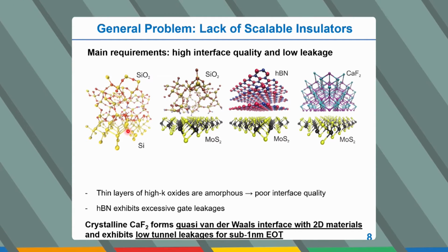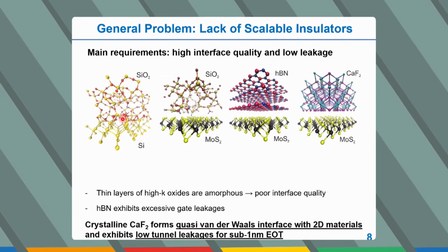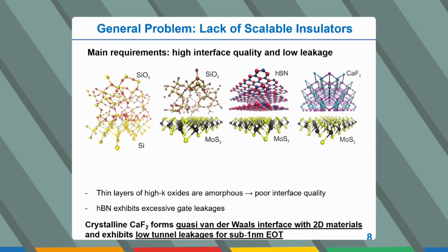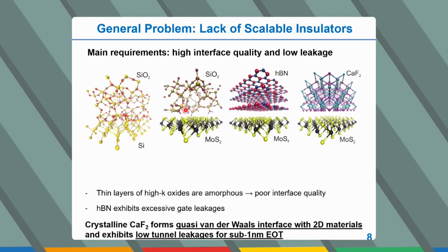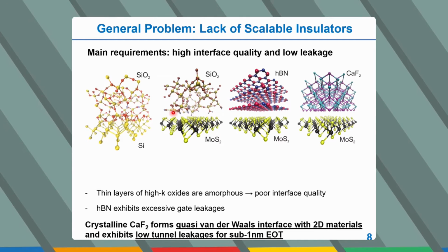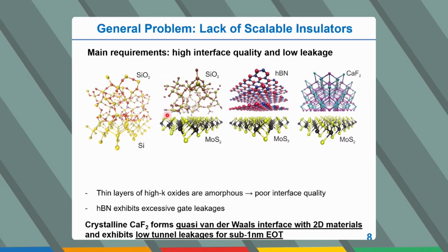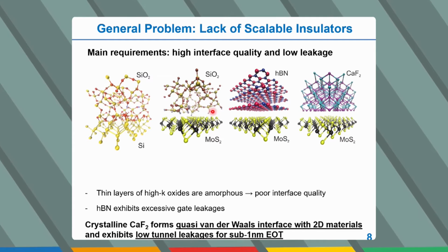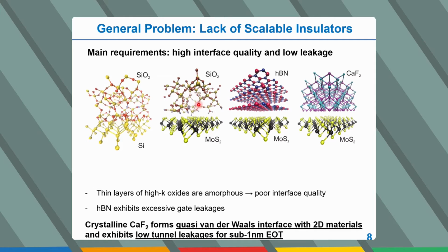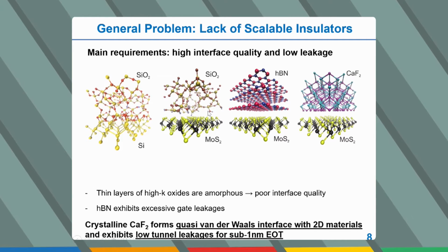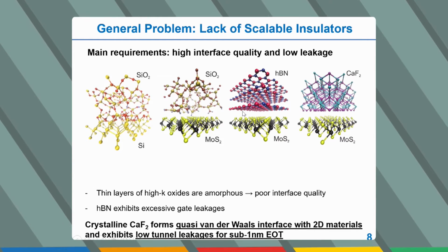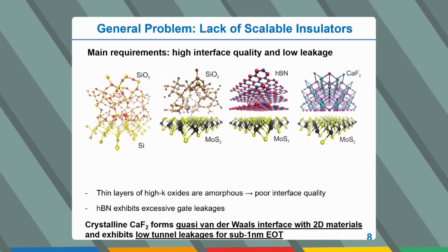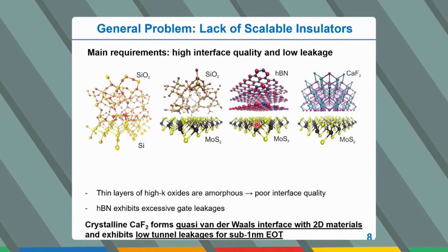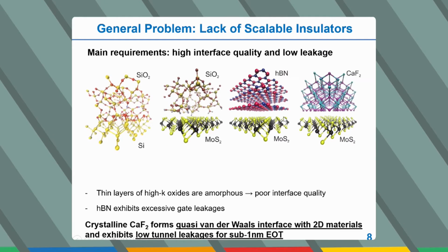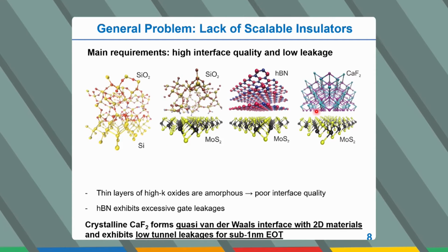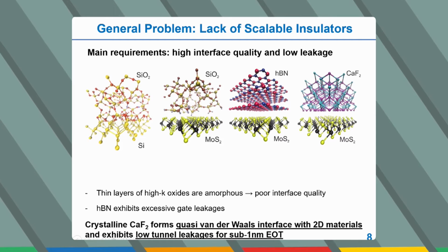In silicon technologies, you have silicon dioxide, which forms a nice native interface with silicon. But when you place a 3D amorphous oxide onto 2D materials like MoS2, you see that the interface is not very good because of dangling bonds, which reduce the mobility, and also oxide defects will perturb stable device operation. A possible alternative is hexagonal boron nitride, hBN, which forms a nice interface, and also calcium fluoride, which we suggested recently, which also forms a very nice interface.